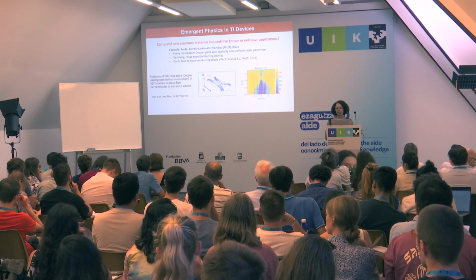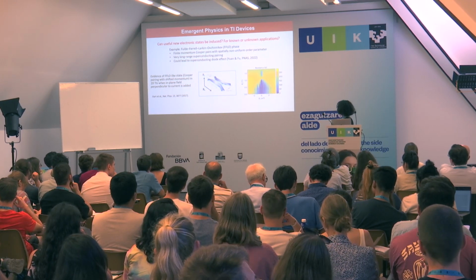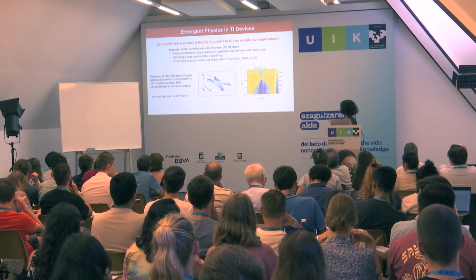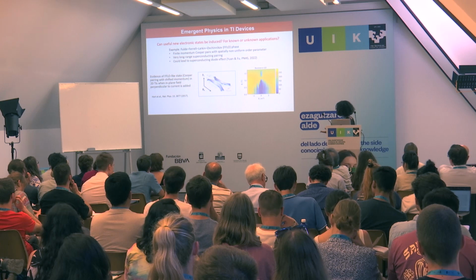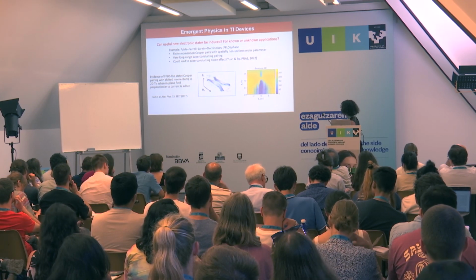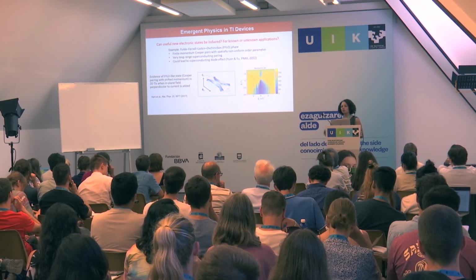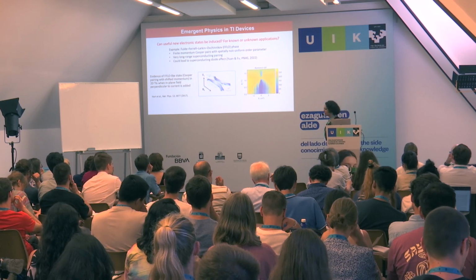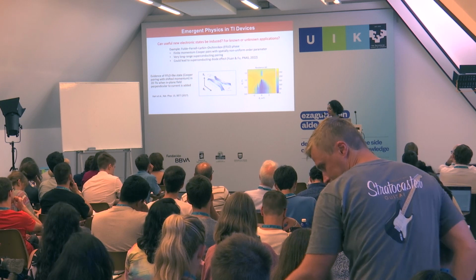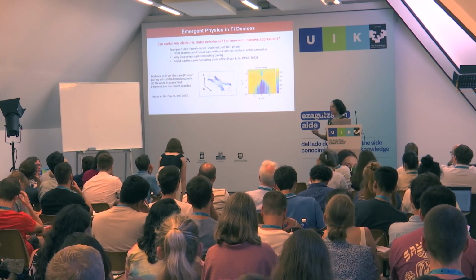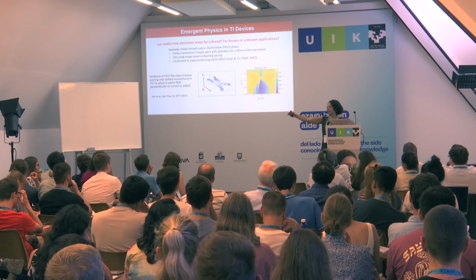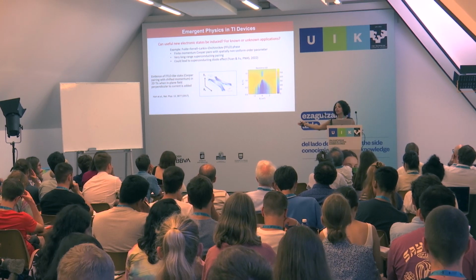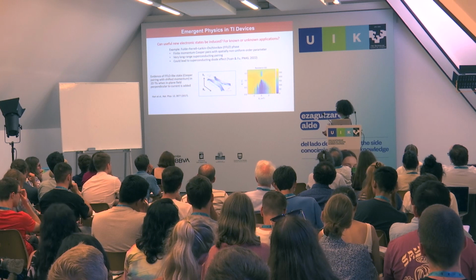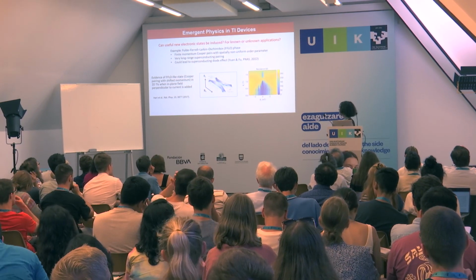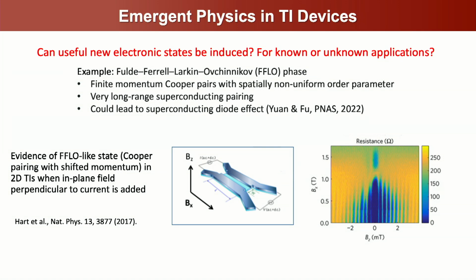I'll talk about that. It turns out that a superconducting junction of topological material that has a magnetic field in two directions on it can induce a state that's similar to an FFLO type phase. That's interesting because you have these finite momentum Cooper pairs that can have very long-range pairing. For most superconductors, as a function of magnetic field and temperature, you lose Tc because of orbital effects. In this case, because you have this additional order through this FFLO phase, you can have much more robust superconductivity up to much higher temperatures and fields. There are even thoughts that this sort of momentum shifting in these systems could lead to superconducting diode effects, for example. So these momentum shifted states have been seen in 2D topological materials.